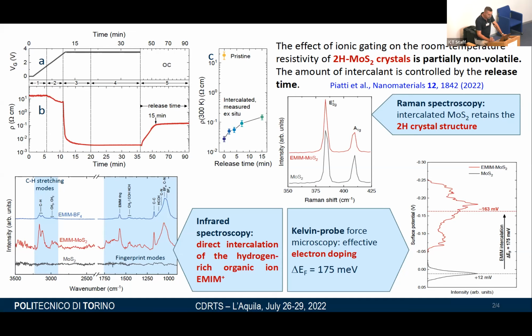So what has happened? We thought to intercalate hydrogen, but this is not the case because, first of all, the samples retain the 2H crystal structure, but what is inside is actually the cation of the ionic liquid. And indeed, you see that this is the infrared spectroscopy spectrum of MoS2. There is nothing. This is the spectrum of the ionic liquid, and this is the material after intercalation.